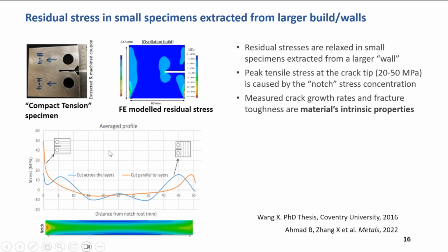materials' intrinsic properties. This is in contrast with the powder bed fusion material, because they only make near net shape material. They don't extract samples. They may polish the surface to remove roughness, and they may just remove tiny small layers. But for the wire arc DED, we actually extract the samples. We extract many of them from one wall, so residual stresses are released.